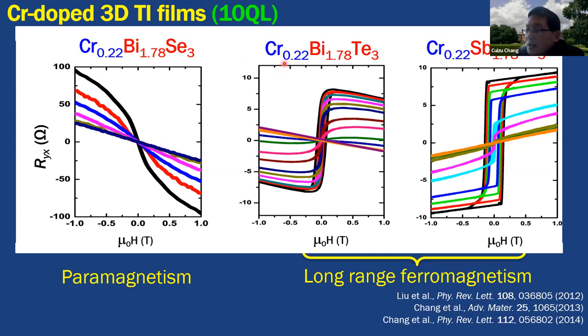And the good news here is the chromium-doped bismuth telluride and chromium-doped antimony telluride both show hysteresis at low temperature. So that means they are ferromagnetic. And the good news here is that this material is N-type and this material is P-type.